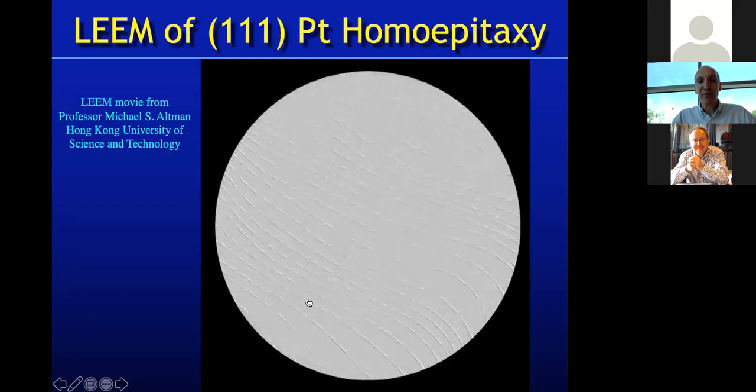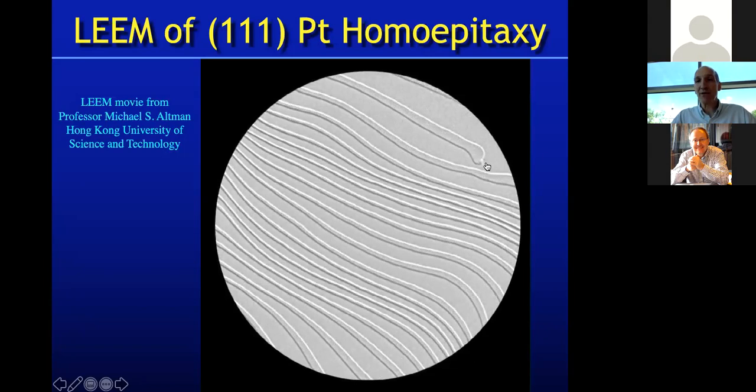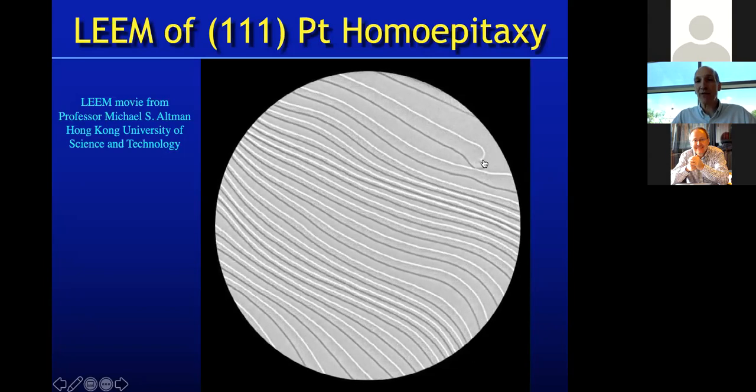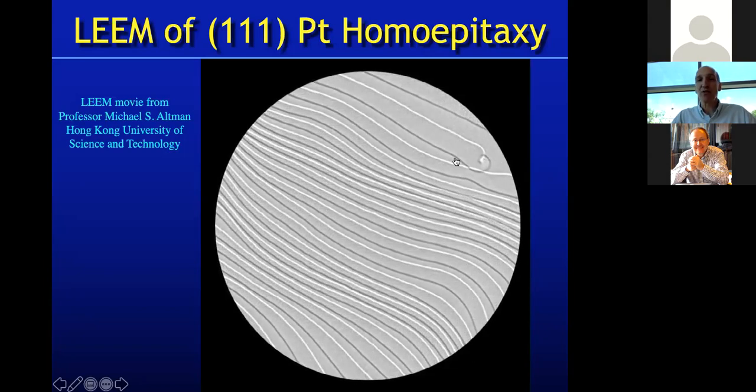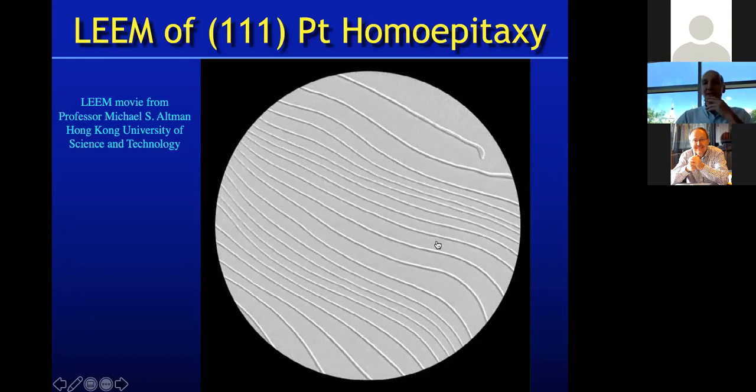And I'll play the movie one more time. If you watch carefully, you'd see that in addition to the step flow, there's also spiral growth happening around this screw dislocation here. So you can clearly see it's not just a drift of the image, but there is actual crystal growth happening by step flow and spiral growth. Okay, so that was example one. Let's now move to